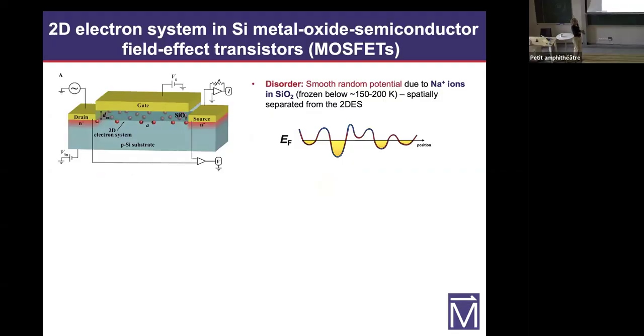Okay, so our experiments have been performed on a system that has been studied for many decades. It's actually the first system in which 2D behavior of electrons was demonstrated. So the 2D layer is formed on the silicon side of the silicon dioxide interface. So this is a silicon metal oxide semiconductor field effect transistor. And so at low enough temperatures, the electrons move just in a plane. We have a 2D system.